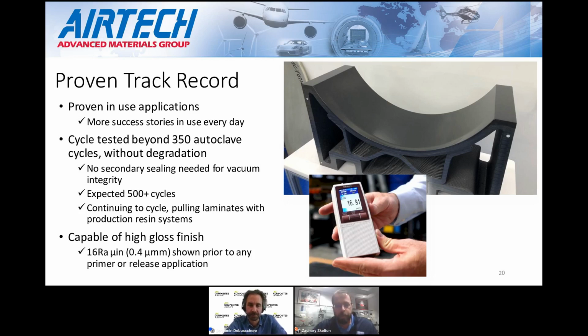And then we can also achieve a very nice surface finish, depending on the requirements. So these are all done prior to any primer or release application. So you can see a 16 micro-inch finish there. So very close to a Class A automotive surface. And we have continued to run some additional trials with polishing to see how good of a surface we can achieve. But Class A surfaces are achievable for automotive applications.